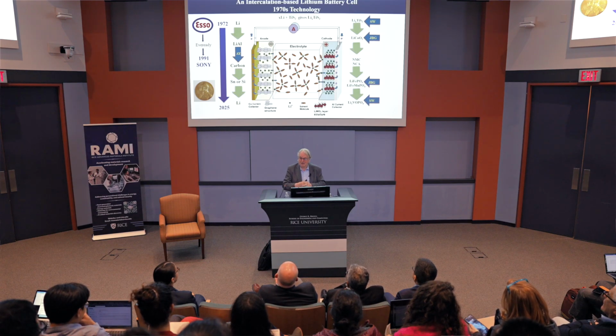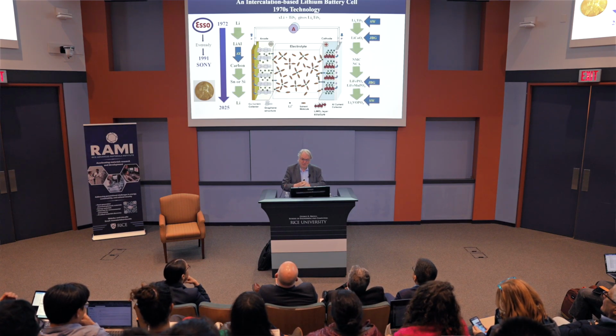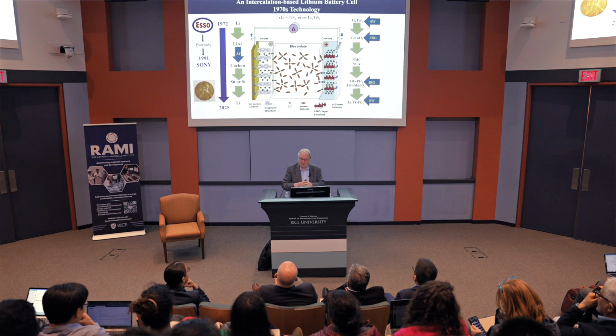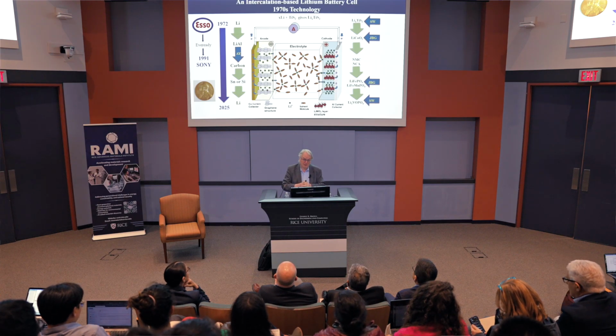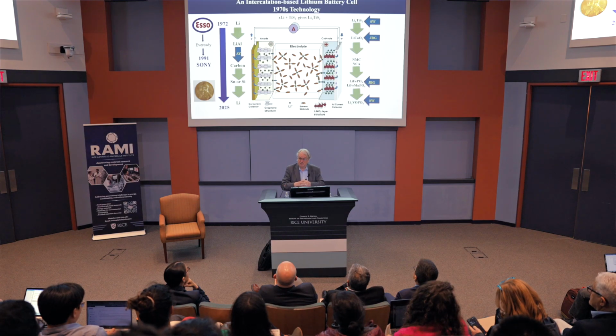So that's when Akira Yoshino in Japan started using carbons, one sort or another, and found you could intercalate lithium into the carbons. So that's where the graphite anode came up. That is what's still used today in essentially all lithium-ion batteries. The graphite is half the volume of the cell. You need 72 grams of carbon to store 7 grams of lithium. So if we want to increase the energy density, we've got to get rid of that.